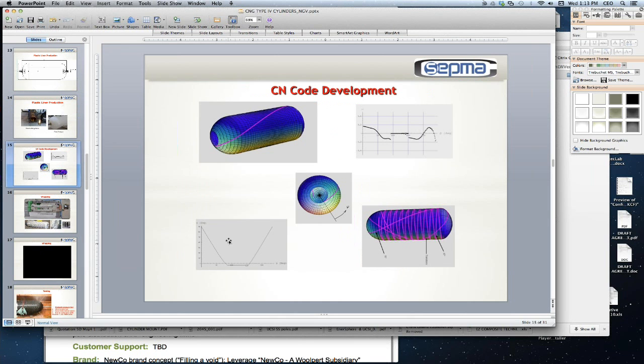The next step typically is development of the code and the laminate buildup. Most of you may or may not know that the strength of the composite comes from the fiber used. So that's why carbon fibers are so popular. They're very lightweight, but also many times stronger than steel. The caveat, though, is that the load is only carried along the direction of the fiber. So it is very important to build a laminate structure that embeds several angles of this fiber in order to maximize the load carrying capacity. This is done by computer modeling primarily, where you need to carefully understand where the highest loads are and how to count